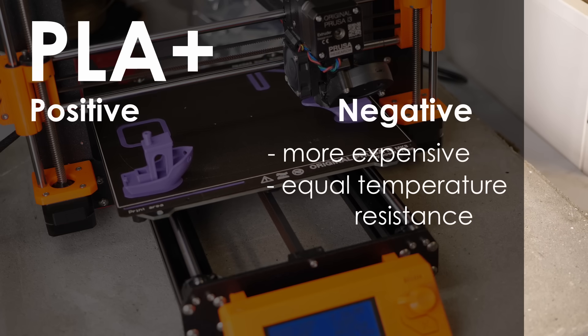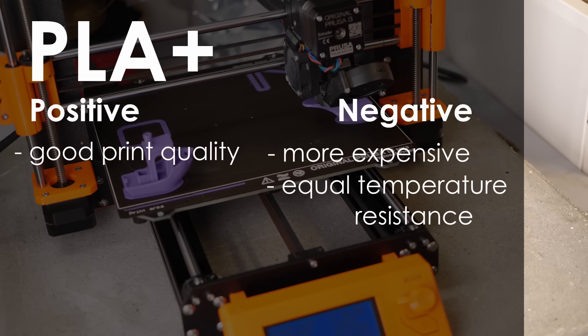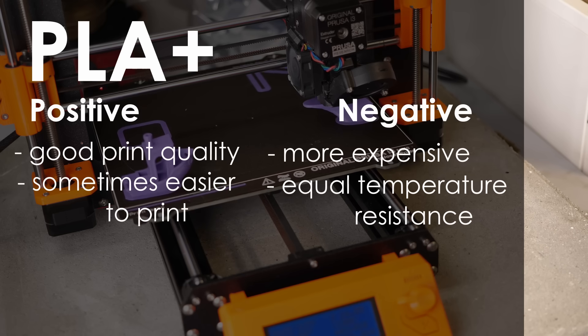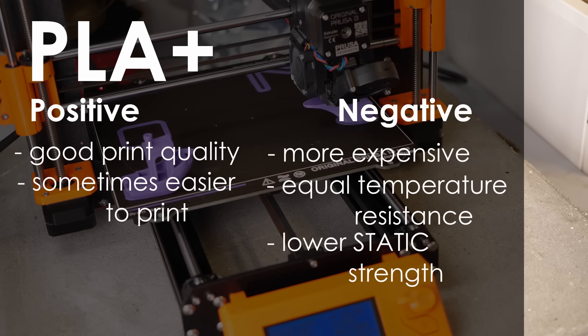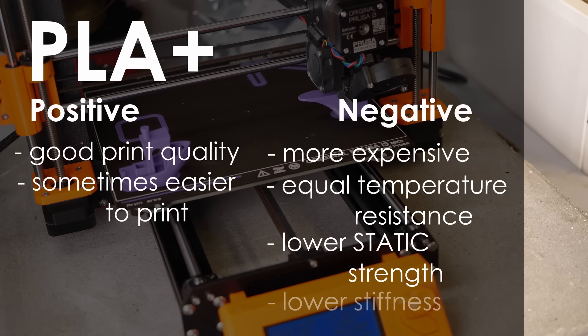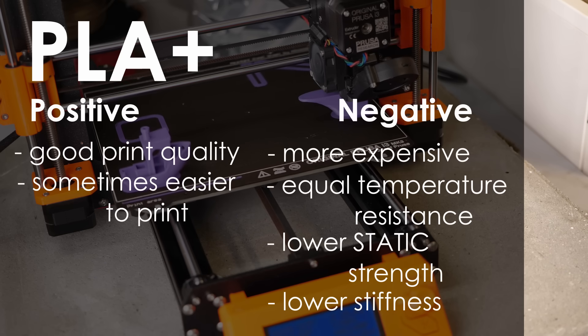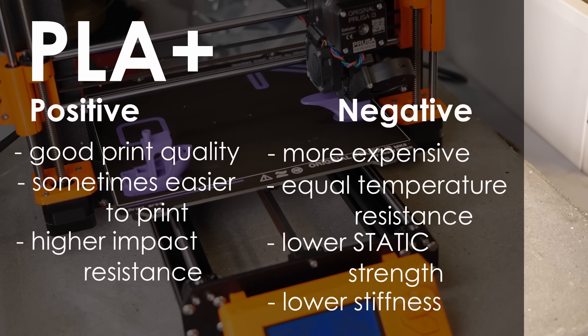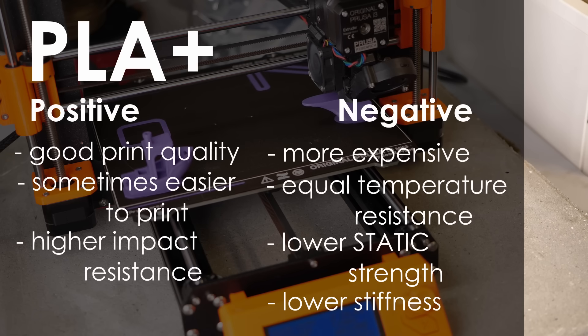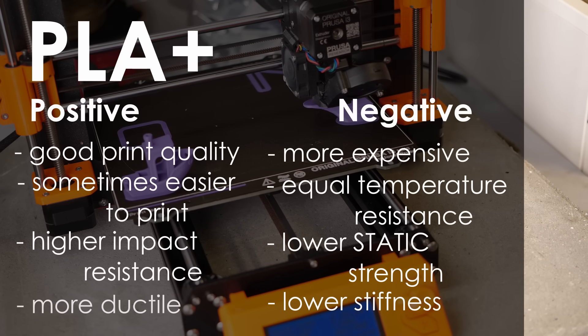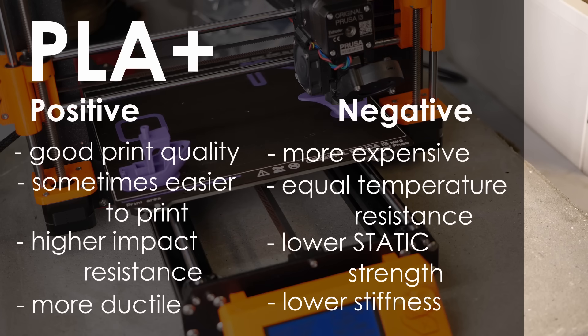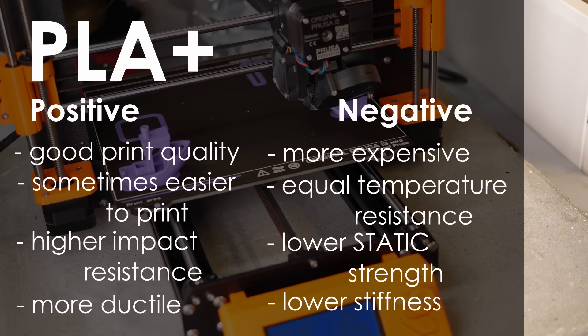It's usually and sometimes also understandably more expensive. Temperature resistance and also print quality is mostly the same. Printability, for example with a Polymax PLA, is definitely improved due to less warping. Static strength is not higher and also the material stiffness can be significantly lower. Where the modified PLAs shine is the impact behavior because here they are usually way tougher than their unmodified counterparts and this also shows in their failure modes. Tough PLA breaks way more predictable because it will significantly deform before it snaps, making it more suitable for some technical applications.